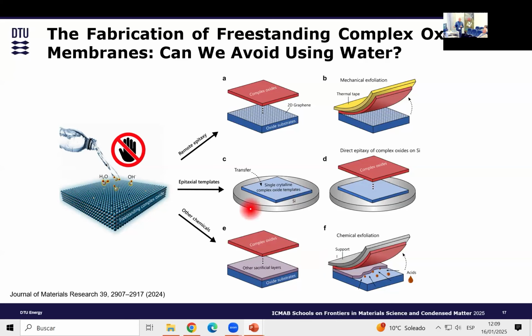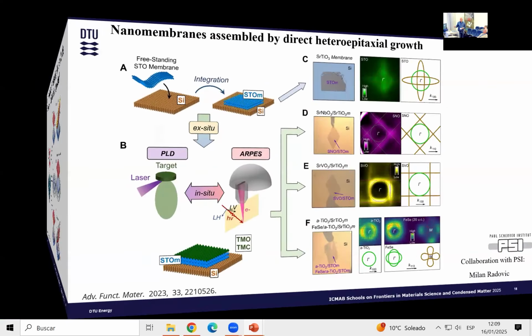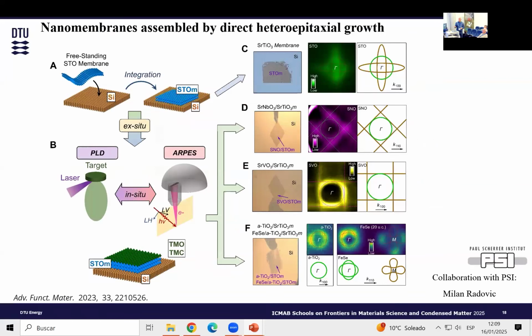There is a third way that I want to show you here, which is using the membrane as a template to grow material on top of it. In that case, you don't need water anymore because you grow it directly with the PLD. We did it together with a group at PSI. We took a silicon, put the strontium titanate on top, and took it in situ into the ARPES to look at the electronic structure of the material, and it looks as good as a single crystal STO.